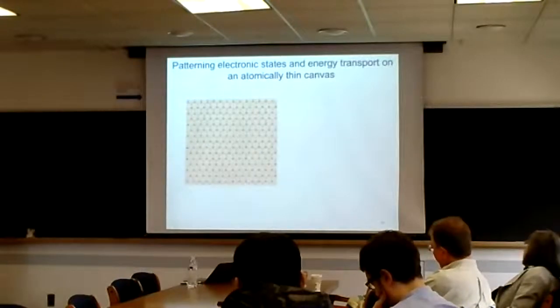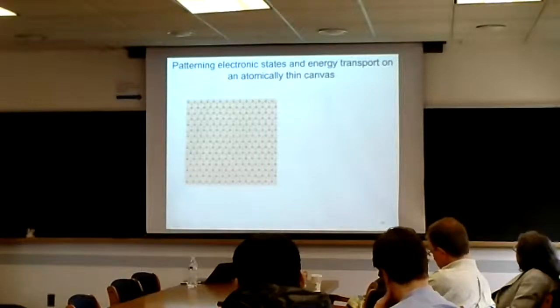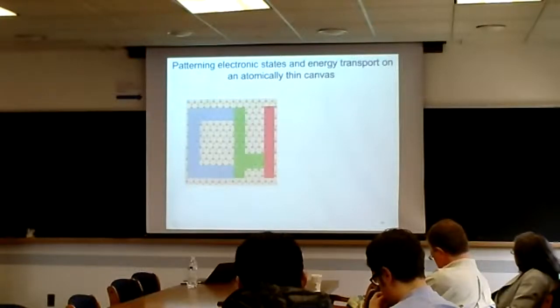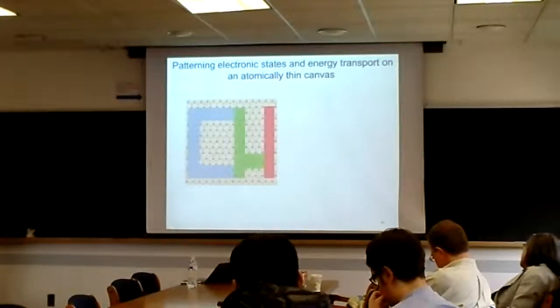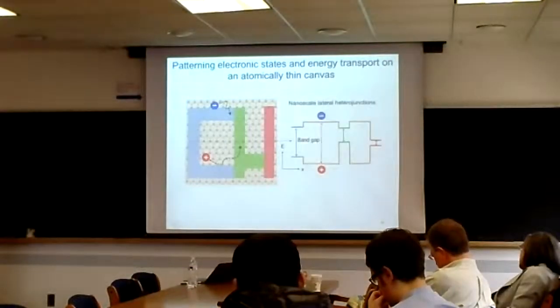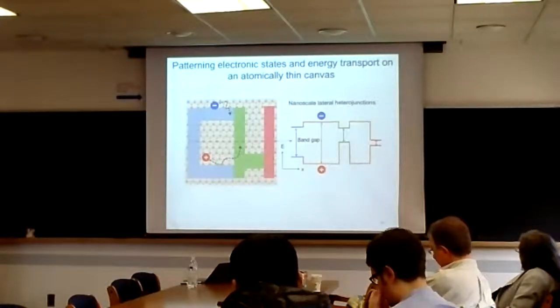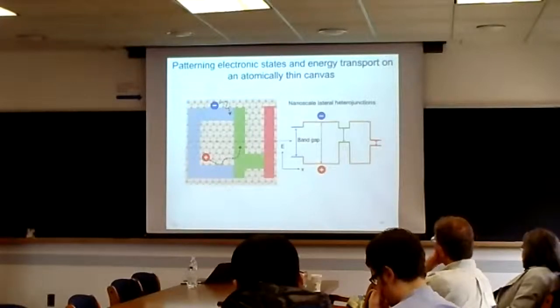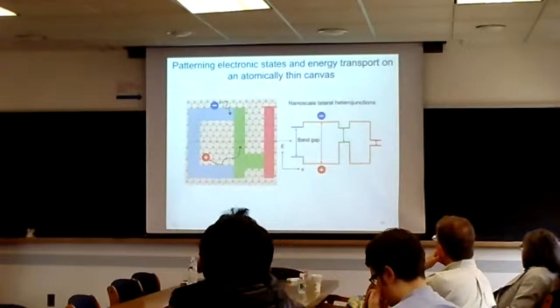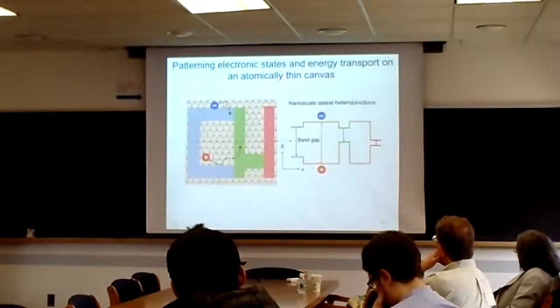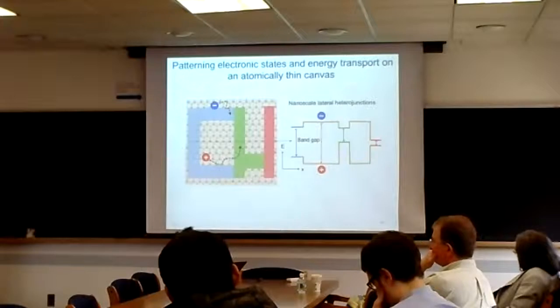So at the end, in my last minute, I just want to leave you with the picture that you have this atomically thin canvas, and you can essentially pattern either new materials on top, or more complex materials on top. But at the end of the day, you can tune electronic structure and create new kinds of heterojunctions, not by changing the material itself, but by purely changing the environment, whether to change the energy transfer rate or exciton-phonon interactions. And that way you can control where these carriers are going from one place to another.